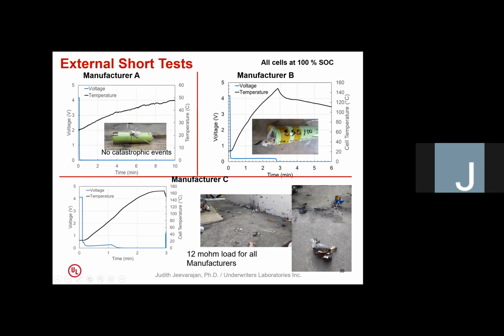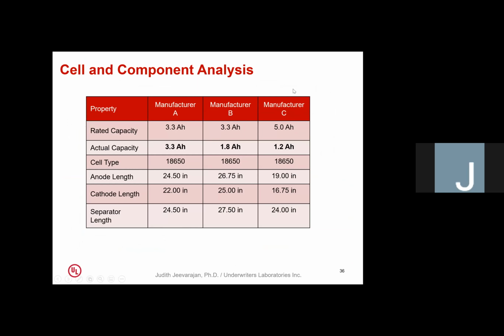With manufacturer B, we did see that it expelled some of its contents under the short circuit study because it does not have a PTC. With manufacturer C, we found that it actually expels its contents like it did under the overcharge test. And you can see in both cases, we did record high temperatures.